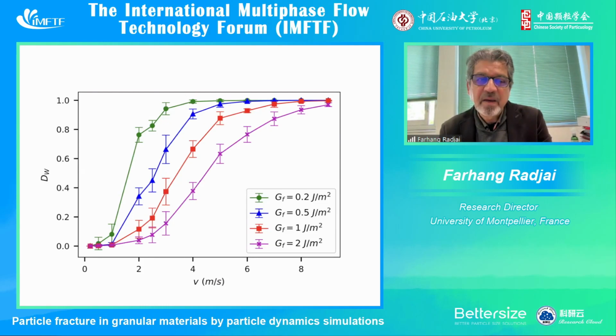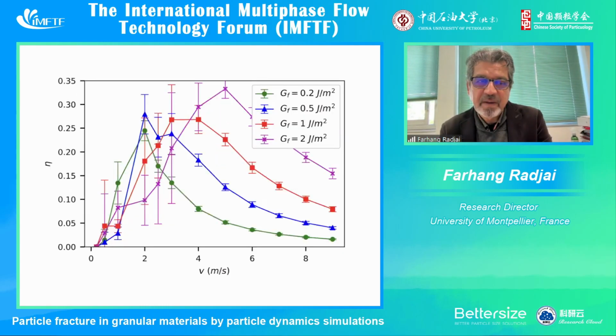In the same way, the efficiency eta increases and then declines. So for an intermediate velocity, which depends on GF, the fracture energy, we have a maximum efficiency. For example, for GF equal to 2 joule per meter square, the peak is nearly 5 meter per second. Here, 30% of the total energy is used for fracture, which is low. I mean, only 30%, that's the highest value that we can get, is used for fracture.